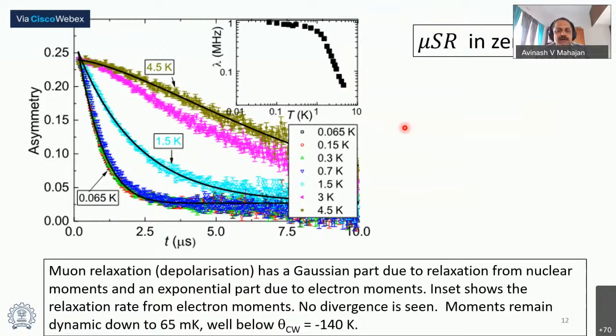Okay, then the local probe that we employ here is muon spin resonance, where you do various kinds of experiments. Here I show the experiments in zero field. Again, to give a very quick introduction, in muon spin rotation and relaxation, muons, which have a magnetic moment, are shot at the sample and implanted inside. These muons are sensitive to the local moment dynamics within the sample. The muon has some lifetime, it decays in about 2.2 microseconds, and gives off a positron.